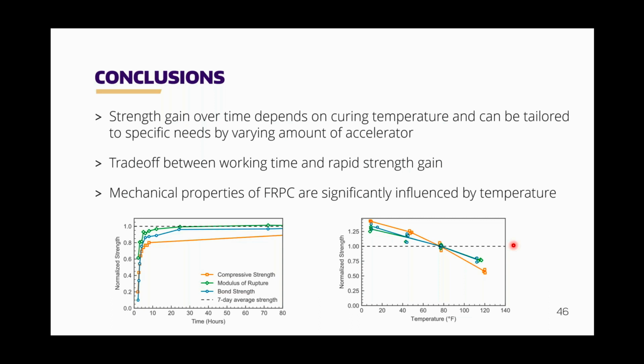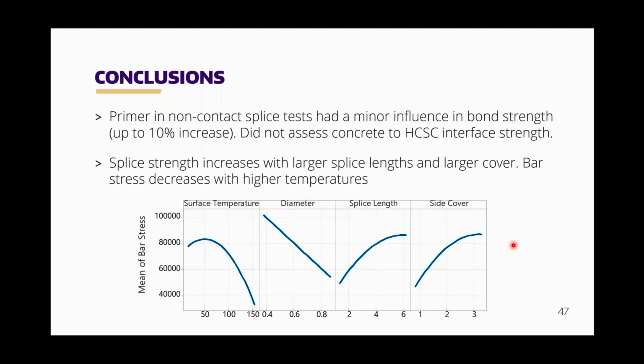There's a trade-off between working time and rapid strength gain. That was that table that Carolyn showed you. The mechanical properties are significantly influenced by temperature, and that was that 25% change, either plus or minus, as you vary 40 degrees Fahrenheit. The primer had an influence on the bond strength, up to about 10% increase. We did not assess concrete to HCSC interface strength, and that's really what the primer helps with, and so it would be important to understand that as well.